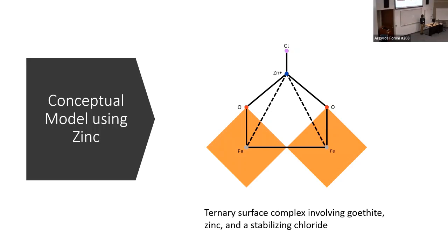And if we were to change out zinc for copper, we would largely see the same thing. One key difference, though, would be that chloride would interact a little more with the surface of the nanoparticle. This would reduce electrostatic repulsion between the metal and the nanoparticle, and therefore allow the metal to be retained more easily. So that is also another reason that we see increased retention in copper when chloride is introduced to the suspension.